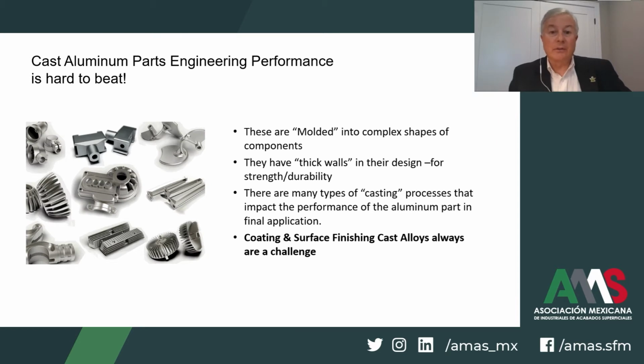The engineering reasons that cast alloys are used are driven by performance. But as already noted, the coating process is very difficult and a challenge unless we take some considerations for their processing. This is why we have developed different types of surface preparation methods for different types of high silicon cast alloys. You should avoid alkaline etching these castings because the complexity of the smuts that form on the surface can be more difficult to remove. However, sometimes alkaline etching is really needed for some pressure cast alloys or forgings, because they do create different smuts, but you have to etch them in a different way. Generally speaking, it's best to stay with an all-acid process cycle for cast alloys, with the exception of first mild alkaline cleaning.